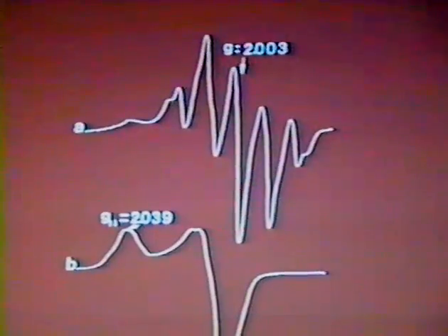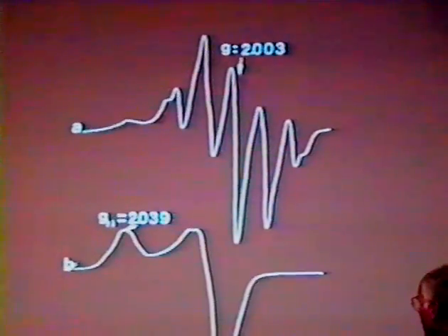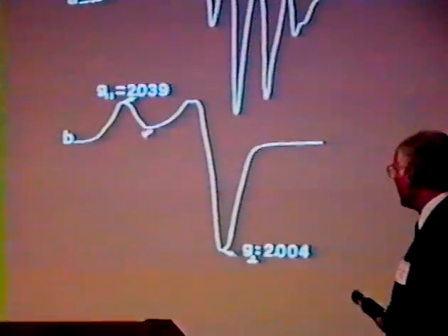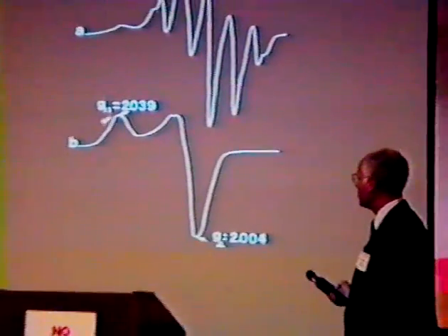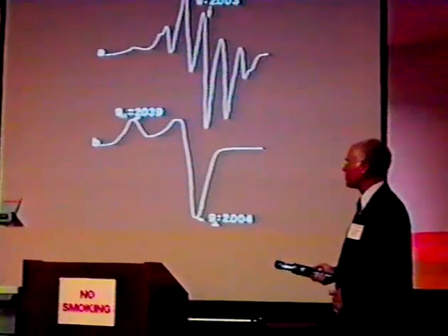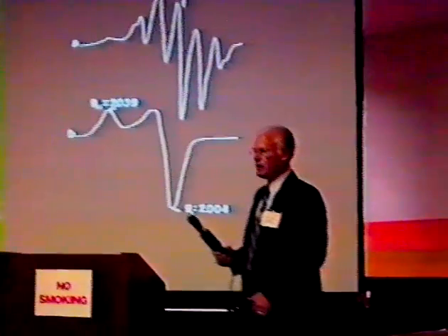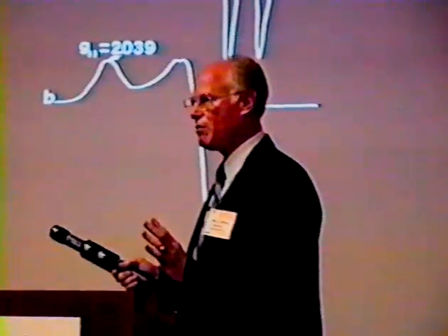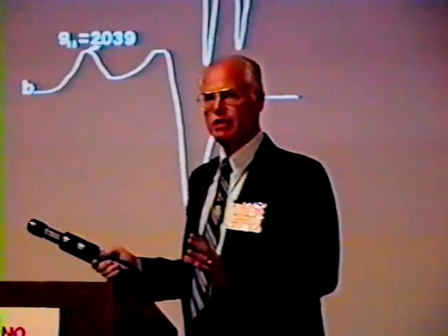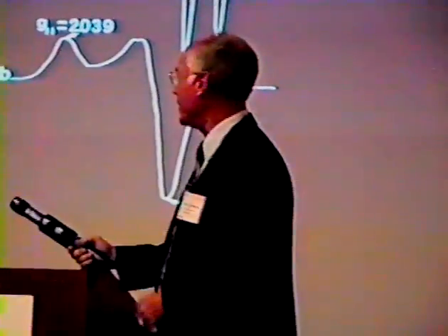And if excess oxygen is present in the system, we form the allyl peroxy radical, which also has a characteristic ESR spectrum associated with it. Now, in the case of the bismuth molybdate, we found that the numbers of radicals formed in the gas phase were relatively small. But when we look at bismuth oxide, we found that quite appreciable numbers of radicals were formed and entered the gas phase.